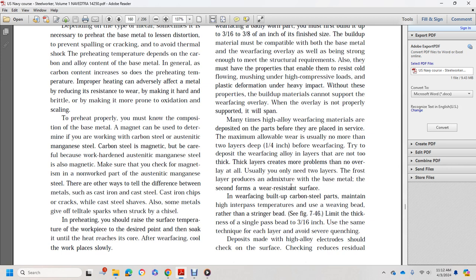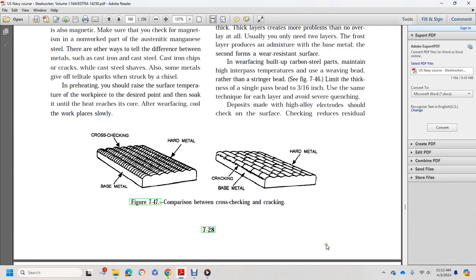When wear facing built-up carbon steel parts, maintain higher interpass temperatures using a weaving bead rather than a stringer bead. Limit the thickness of a single pass bead to 3/16 of an inch using the same technique. Use the same technique for each layer and avoid severe quenching. Deposits made with high alloy electrodes should be checked for surface cracking, with reduced residual stress. Figure 7-47 shows a comparison of cross-checking, cracking, base metal, and hard metal.